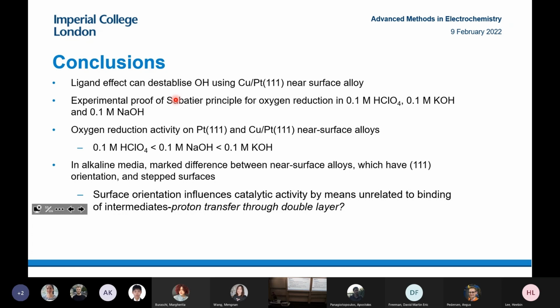Another thing worth bearing in mind is that oxygen reduction activity on these different surfaces is a lot lower in acids than it is in alkaline media, something that hadn't been reported before. I've seen a lot of papers saying that you always have higher activity in alkaline media. That's not the case for these surfaces. And there's a marked difference in alkaline media between the behavior of near-surface alloys, which all have 1-1-1 orientation, and step surfaces. So I think there's something else happening, some additional barriers on the step surfaces controlling the reaction.